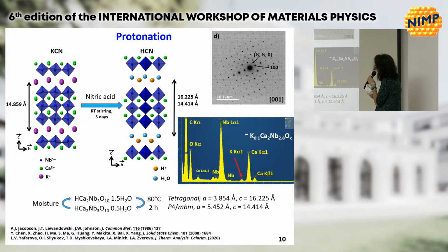The first step is to put the powder in nitric acid at room temperature with stirring. It takes 3 days to exchange the potassium ions by protons from the acid. And you obtain another layered compound. And again, we can check the materials. For instance, by measuring the composition by energy dispersive spectroscopy, we can see that we have lost almost all the potassium in this material.